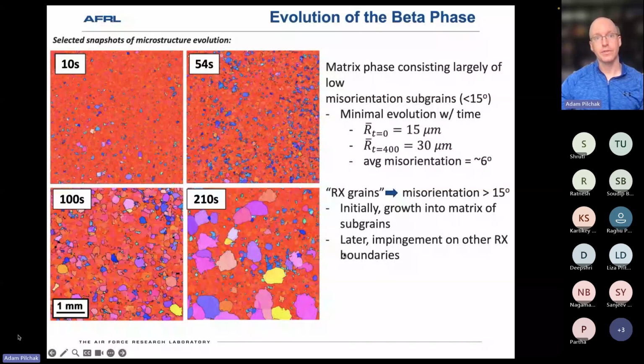The recrystallized grain size increases, but the subgrains remain relatively stagnant. So even all the way up to about 400 seconds, the subgrains had only coarsened by a factor of 2, with the average misorientation staying pretty close to where it was. However, as you can see here, the recrystallized grain size got as large as a millimeter or so. So initially, these recrystallized grains are growing into a matrix of subgrains, and then later, eventually, you get impingement between the recrystallized grains and a transition to more of, say, curvature-controlled grain growth.